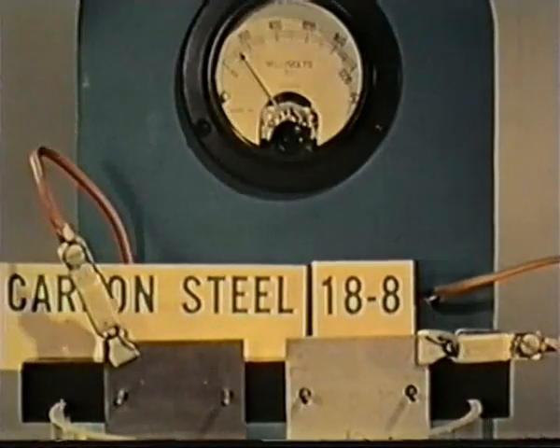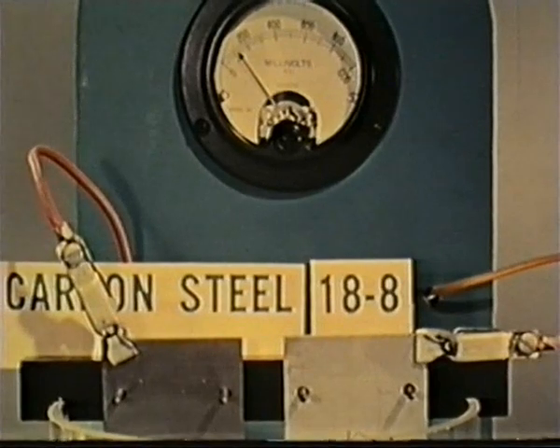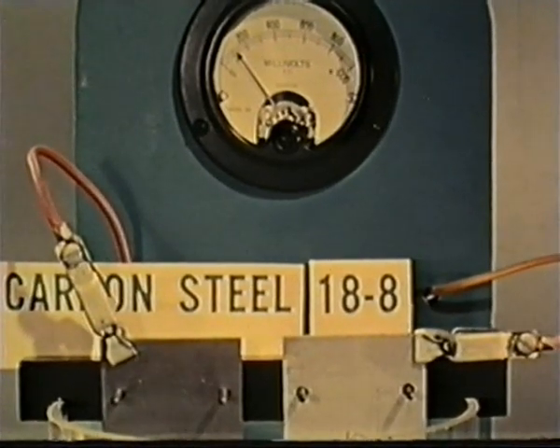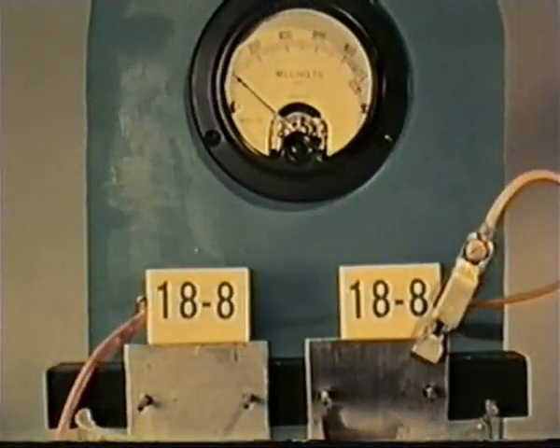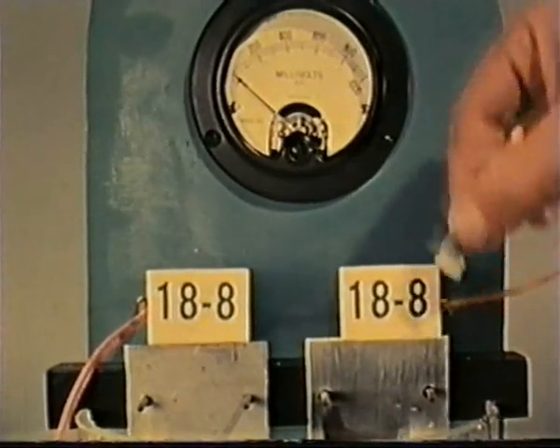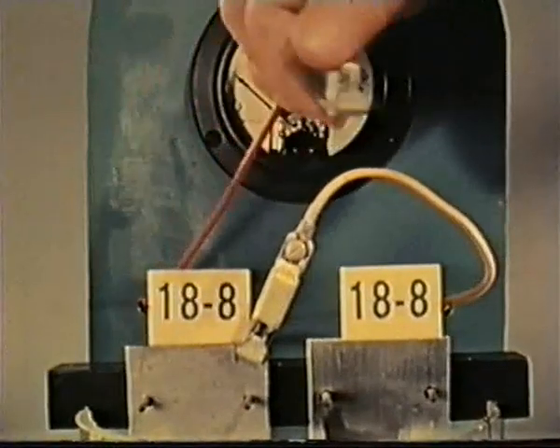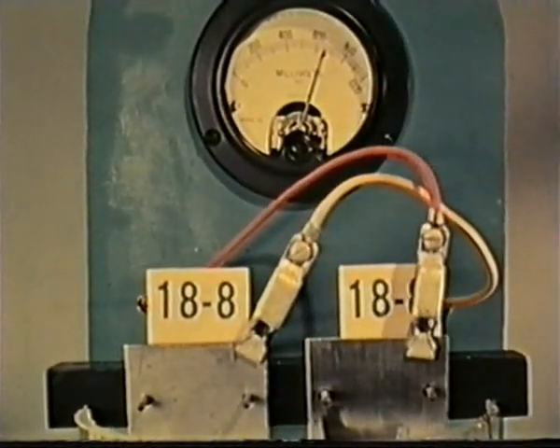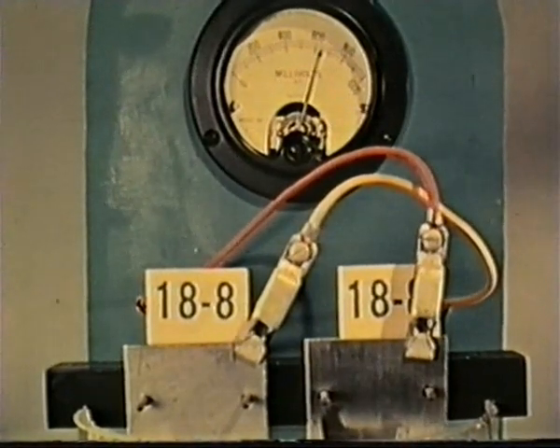When we take the piece of carbon steel away, we find that the potential difference between the stainless steel and carbon steel has fallen towards zero. Now let us introduce a piece of stainless steel that is still passive. We see that the potential difference between this passive steel and the activated stainless steel is as great as just observed between ordinary steel and the passive stainless steel.